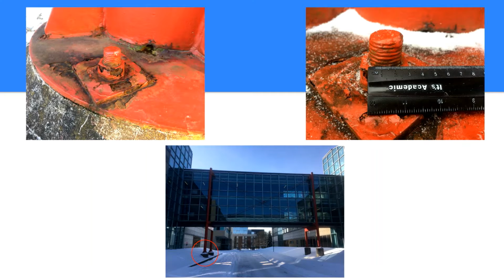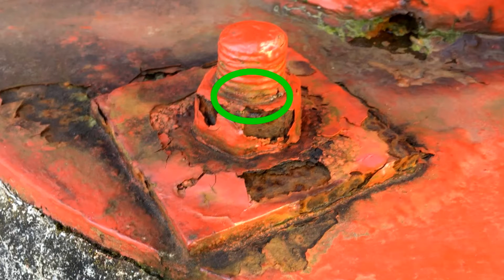The bolt was designed to work outside in all weather conditions, so in order to avoid corrosion it was painted to ensure no water or other electrolytes were able to enter the crevice between the nut and the bolt in order to avoid crevice corrosion. However, it can be clearly seen in this photo that paint has long flaked away, leaving room for water to enter, especially where the nut and bolt meet.